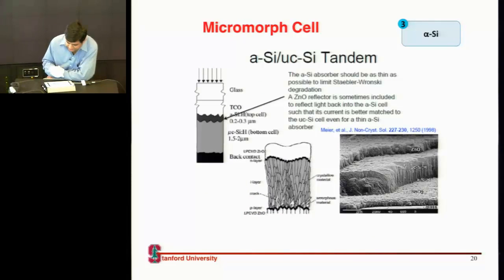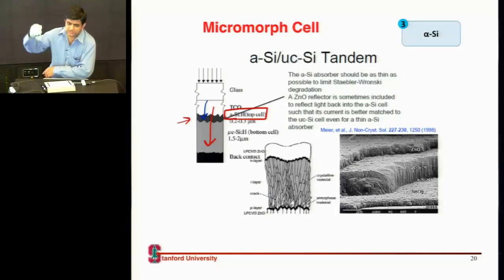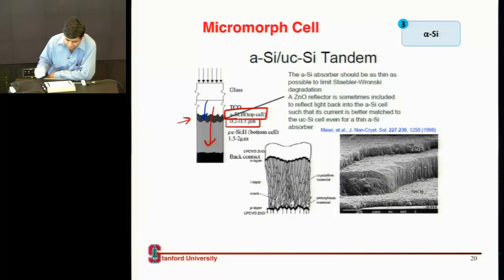So this is the idea which people explored at that time, and you use a thin layer of amorphous silicon to make the top cell. So this will absorb your blue light, and then all the red light and the green light would be absorbed by this microcrystalline silicon. The thing with microcrystalline silicon is, again, it's not a very good absorber of light, just like silicon, so you need a much thicker amount of it. So these layers were, the amorphous part of it was very small, 200, 300 nanometer. The microcrystalline part of it was 2 micron.